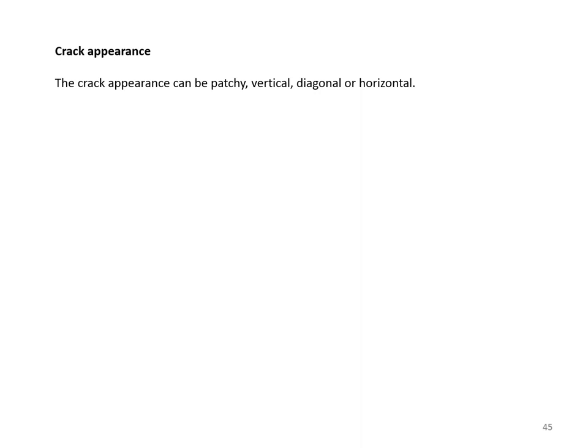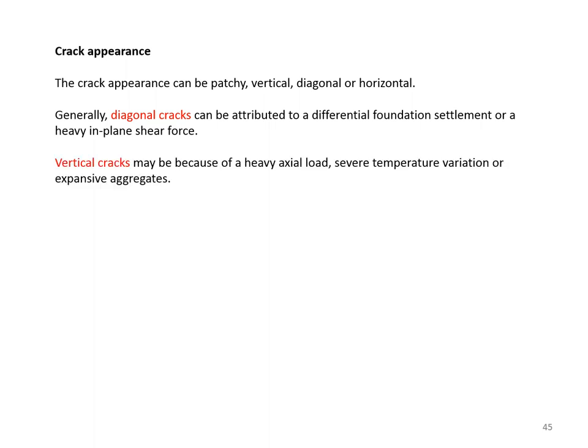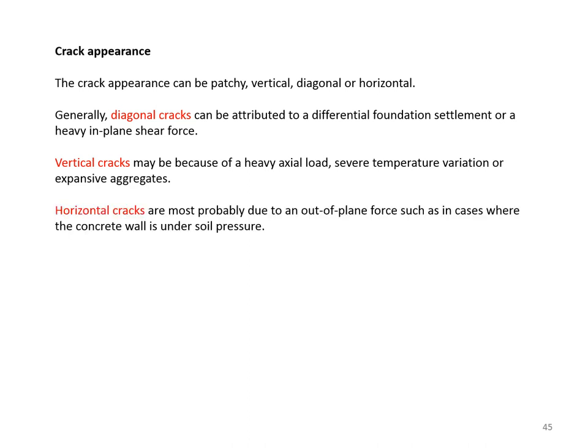Crack appearance can be patchy, vertical, diagonal, or horizontal. Diagonal cracks can be attributed to differential foundation settlement or heavy in-plane shear force. Vertical cracks may be due to heavy axial load, severe temperature variation, or expansive aggregates. Horizontal cracks are most probably due to an out-of-plane force, such as in cases where the concrete wall is under soil pressure.